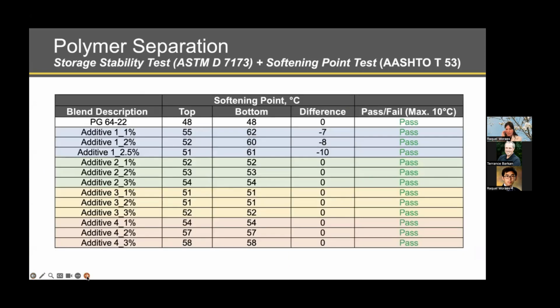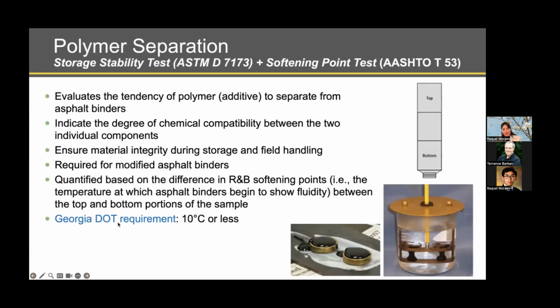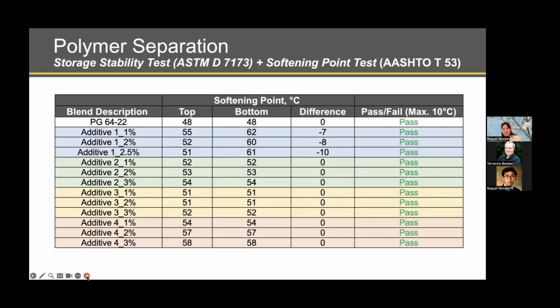As you can see here in this table, we use the pass/fail limit as indicated in the previous slide of the Georgia Department of Transportation, which requires that the softening point temperature difference between the top and bottom portion of the storage stability test cannot be higher than 10 Celsius degrees. As you can see here in this table, for all the additives at the 3 dosages evaluated, none of them give us a difference between top and bottom portions higher than 10 Celsius. For additives 2, 3, and 4, all dosages show actually a difference of 0, so no separation. And the only product that showed a higher tendency for separation was additive 1.